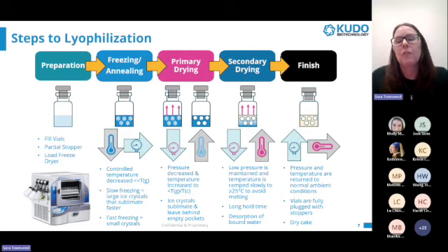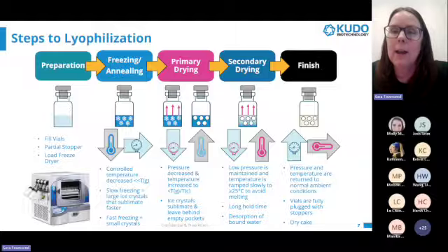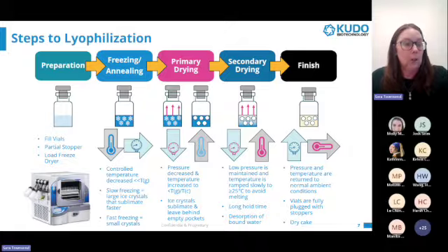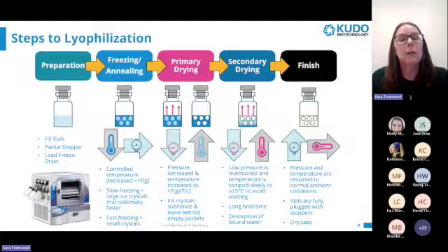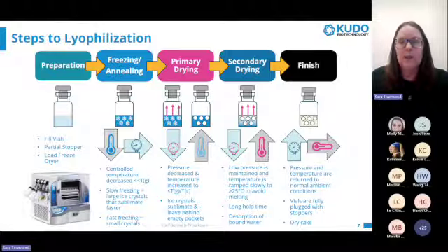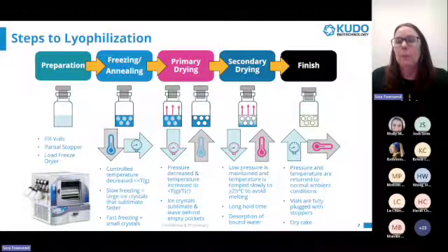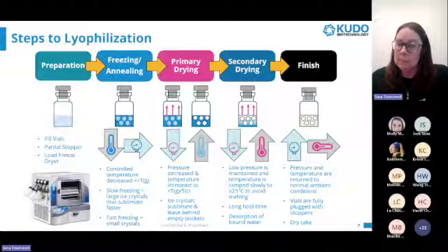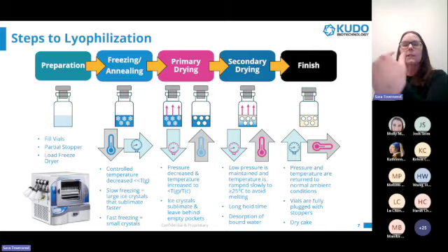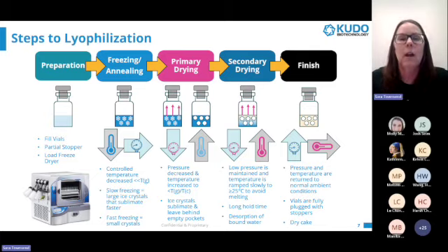The next step after the freezing step is primary drying. The pressure will be decreased considerably and the temperature increased, but still kept below Tg'/Tc. At this point, based on that temperature and pressure differential shown on the previous slide, the ice crystals will sublimate and leave behind some empty pockets. After this step is completed and all of this free water has been sublimated, the next step is secondary drying.